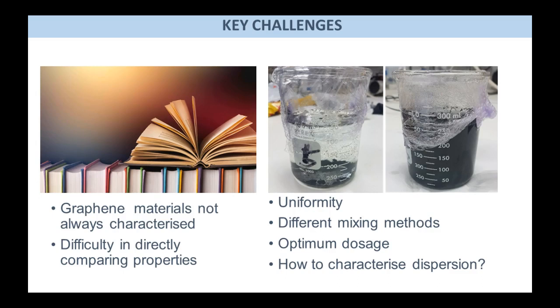When you add graphene, by the way, I have graphene in powder form in this case. When you add graphene, it tends to agglomerate very quickly and it doesn't mix in water at all. And then you need some sort of chemical or mechanical treatment to make sure that it mixes homogeneously first before you add it in cement. So over the last 2 years of my PhD, I've tried loads of different mixing methods, loads of different chemical and mechanical methods to find an okay method to disperse it homogeneously. And we've done a lot of work with that, with Heidelberg cement to understand that homogeneity when you mix.